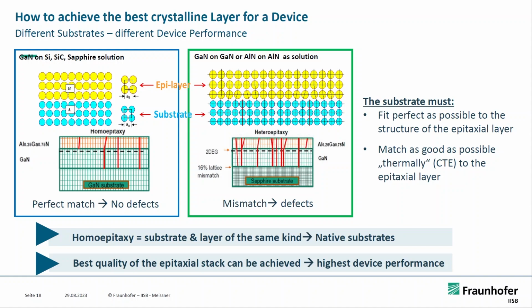Whereas in heteroepitaxy, the materials have to be adapted in terms of lattice match, but also in terms of CTE match. If you heat and cool during the process, you might bend your wafers. The atoms need to accommodate for mismatch, which is why you create mismatch dislocations. So we always have a higher defect system in heteroepitaxy.